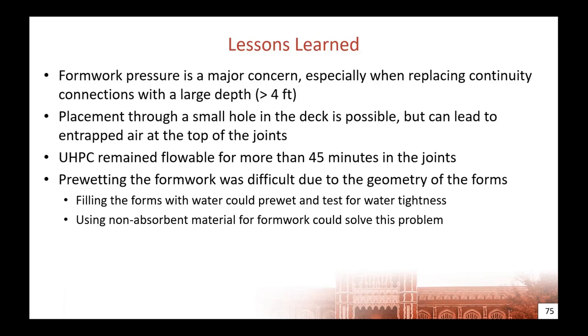That's a good point. We didn't see any additional cracking or damage just from the construction procedures. But just of note was that because of the damage on the joint, it was more or less assumed that it was behaving simply supported. And UHPC, the beauty of this material itself, is it gained strength pretty fast. So it was probably at 4,000 PSI in about a day. Once it finally hit final set, it gets to the strength of the joints pretty quick.